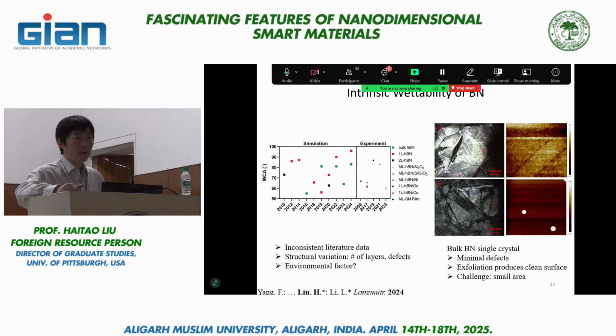And on the bottom, I show the wettability measurement. On the left is fresh. Here we did something new. We measured not only the static contact angle, but also the advancing and receding contact angle, trying to get more additional information about the nature of the surface.